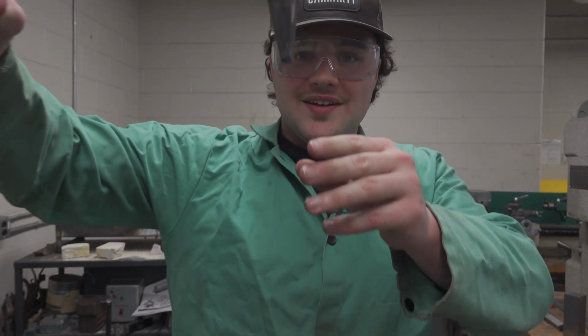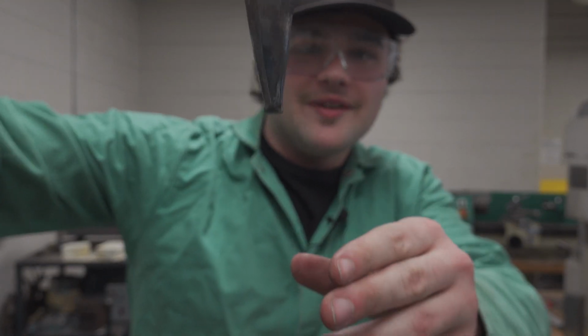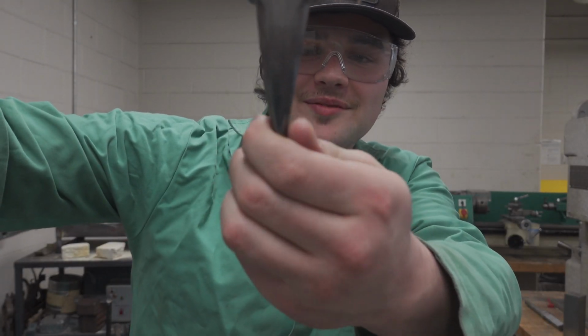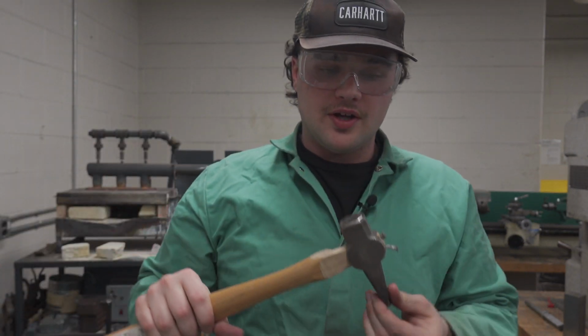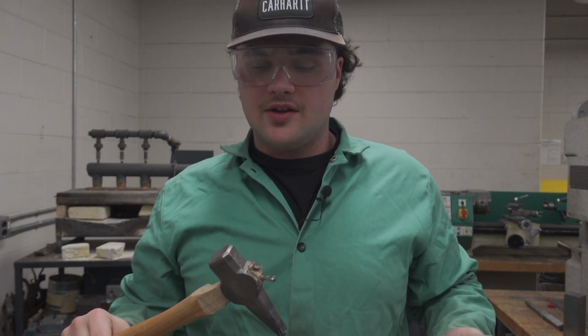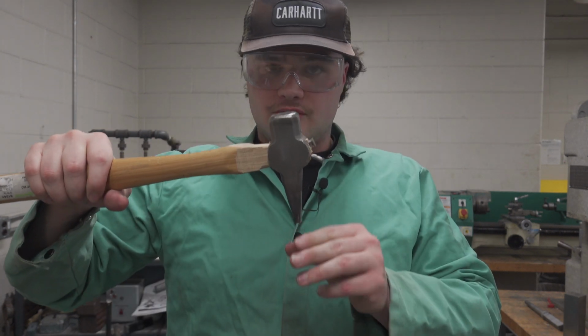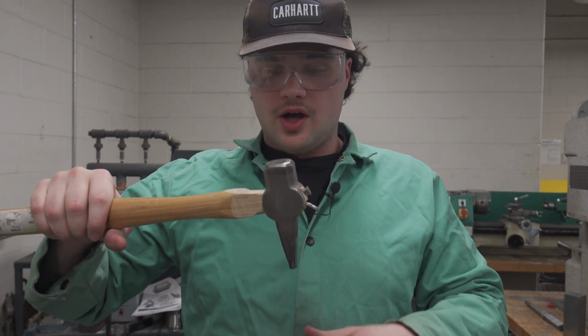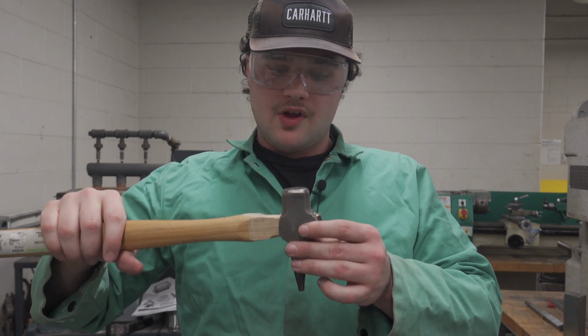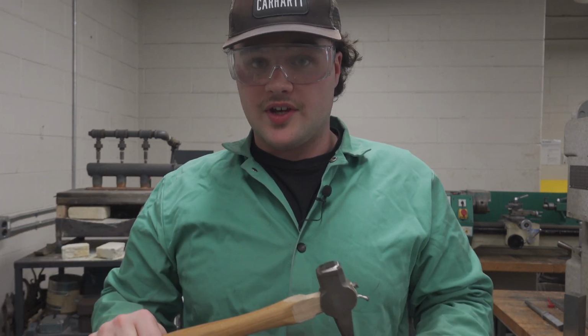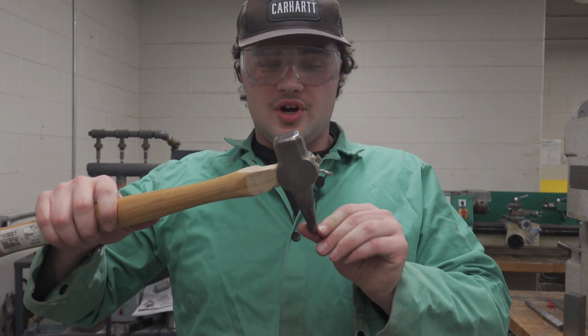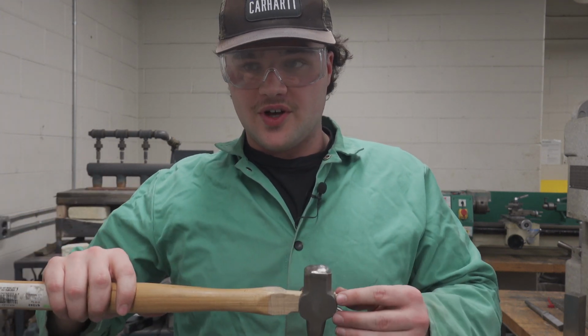It wasn't as bent as it is now. Maybe if I straighten it a little bit, but it got pretty bent just because of the harsh temperature gradients of this being cold and our workpiece being hot. But we were eventually able to punch a hole out through the material, and that was a lot of work. That probably took us like 3 hours. But it was definitely rewarding when we saw the little plug.